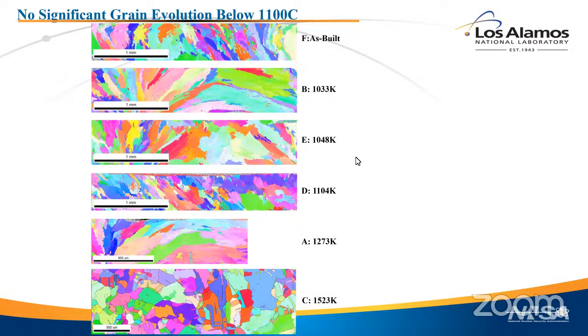Well, we're almost done. C, you can see complete recrystallization. Okay, so by going to 1500 Kelvin, we've now changed the grain morphology. So that's another microstructural feature that we took out. And then finally,